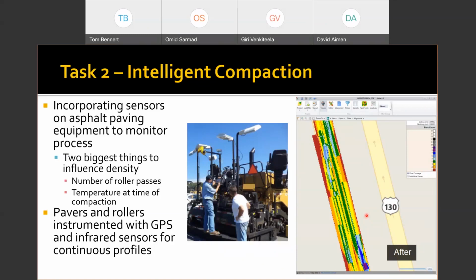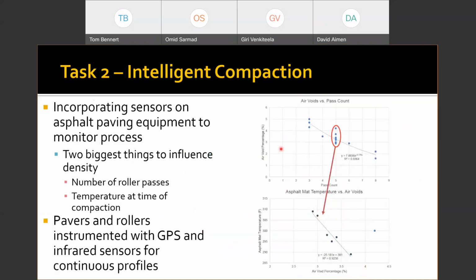Because the lower the density of the material, the higher the air voids and the more likelihood you're going to get accelerated aging. So we look at these things and combine the number of passes with the infrared to get an idea of the number of passes versus density, and we can look at how well these pavements are being constructed. The equipment operators can look to see where they've gone and where they have to go. And we can explain anomalies like this, where at 5 passes we have air voids between 4.5 and almost 2.5%, but that was simply because of the difference in temperatures that we're seeing on the pavement. So we can look at combining these technologies to help improve our construction.